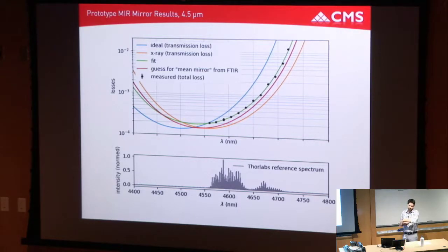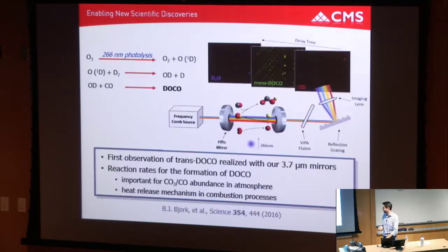And if you bring the transmission down, then you can shoot for 50, 60, 70,000 finesse in the cavity, with the next step trying to go to a 100,000 finesse cavity at 4.5 microns. But these losses are beyond our state-of-the-art for mid-IR reflectors. Even our first prototypes, it was very nice to get some cool scientific output.